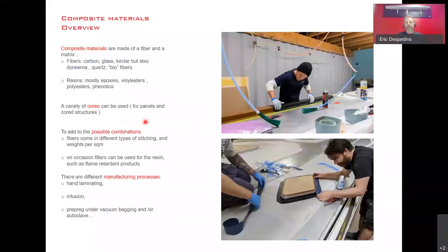And to add to the combination, you've got different brands of fiber, different weights of fiber, different ways of stitching the fiber. You can use different fillers for the resin. For example, if you need a flame retardant product, you can mix that in the resin. And then you have different manufacturing processes. So you have Rhys on the right-hand side here doing a wet laminate on the beam. That's hand consolidated, you brush in the resin and make sure everything's consolidated. And Alex and Andrew here are laying down some prepreg. This is the start of a bulkhead on the table.